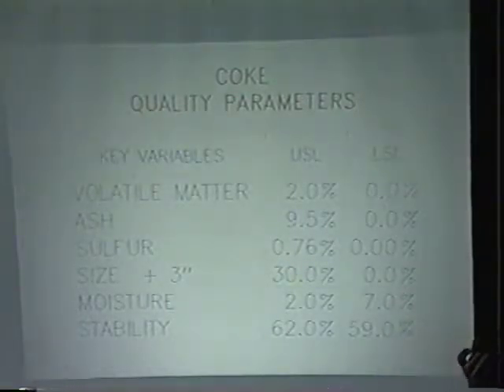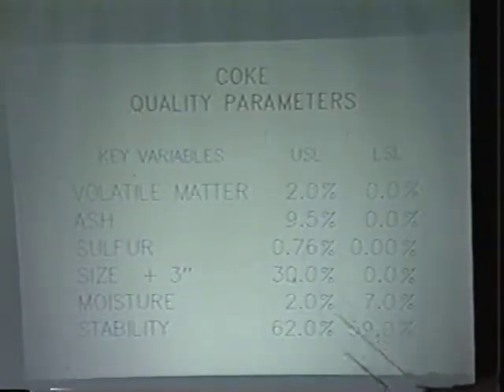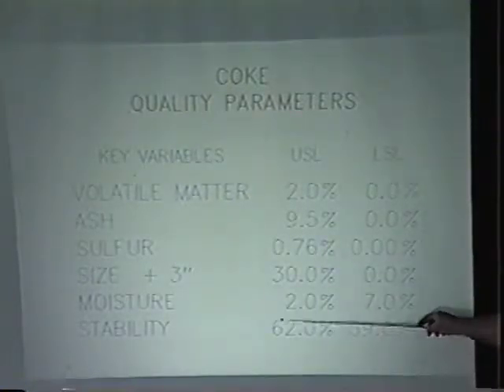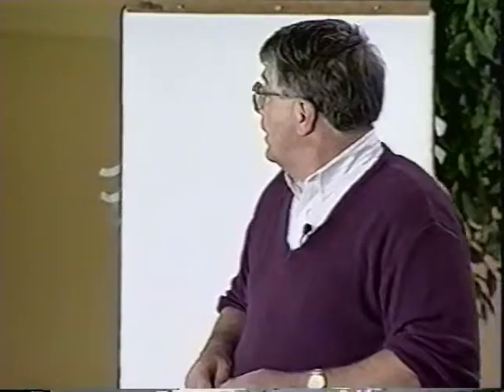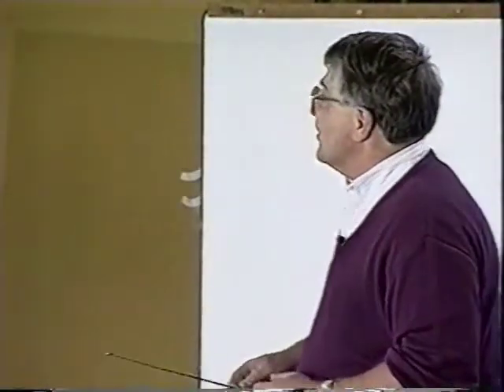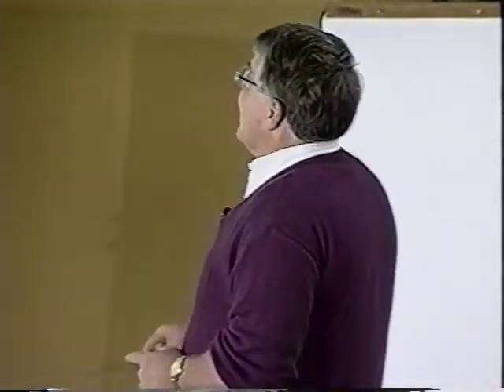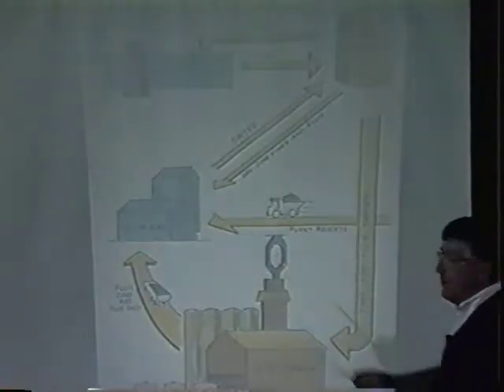Size is very important because we're looking at a certain size going into the blast furnace. Moisture, we talked about that earlier. We don't want the blast furnace to be using their fuel to get rid of our moisture. And then stability is that strength number. And they actually measure that. They do a lab test, and that's an interesting thing because the blast furnace looks at stability and they say, you're not giving us high enough stability. And the coke oven says, we're doing the best we can. So it gets a little interesting, but now we'll go to the sinter plant.